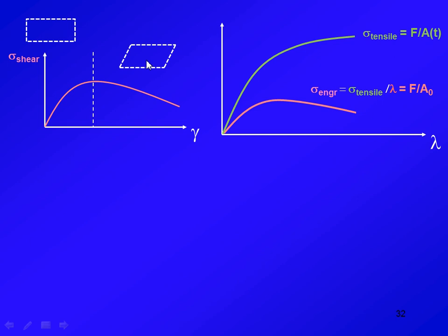If you do extension, traditionally, we treat polymer as a liquid. Liquid doesn't remember its history. Therefore, we like to think about a quantity that updates itself momentarily, and therefore we look at true stress. That is the tensile force divided by the instant area that's shrinking upon extension. If you look at that signal, it strongly grows because of elastic deformation. And then it starts to soften, meaning the growth of that tensile force starts to be less strong, less rapid. But it's still monotonic, therefore somewhat featureless.